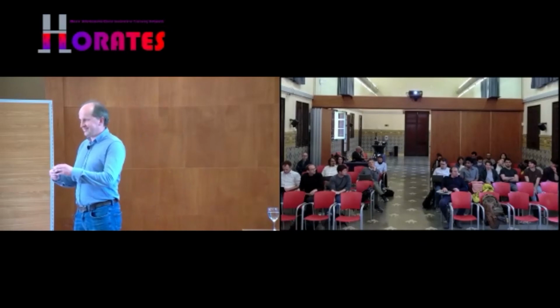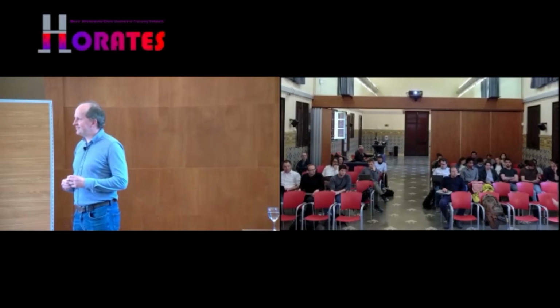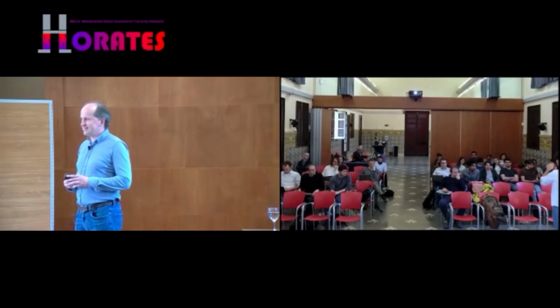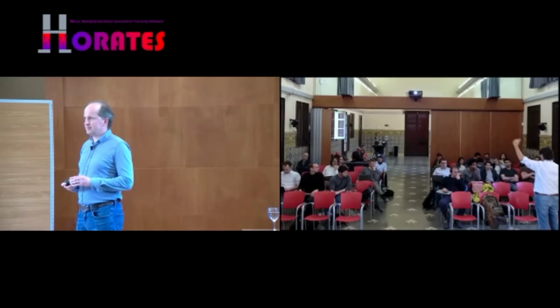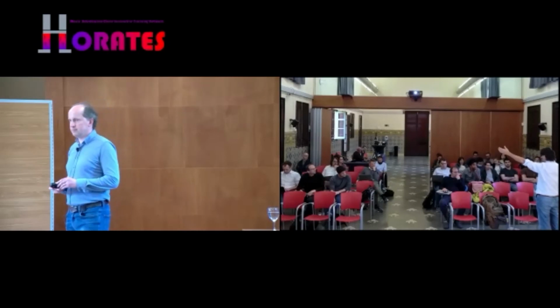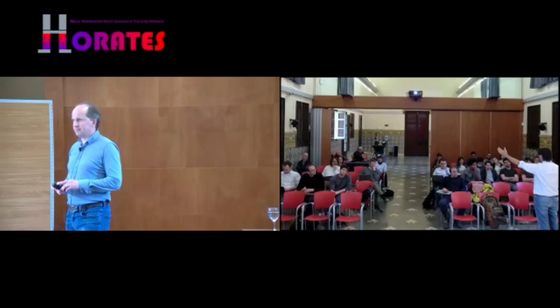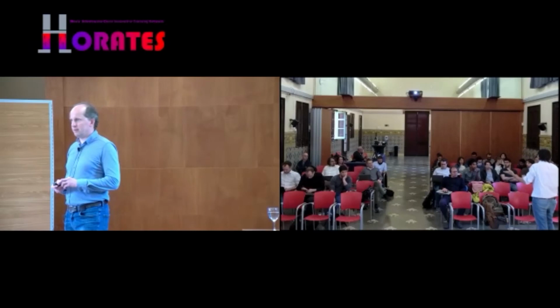Anybody else? If I may comment something, maybe I'm wrong also, but probably you focus more on the modes with the highest speed of sound, right? The modes which are flat, the dispersion is flat, the group velocity is very slow, so the contribution to the thermal conductivity is relatively low. So actually you want modes with a large slope, which are the ones that probably will carry more heat. And this is the typical comparison that you make between the longitudinal acoustic and transversal ones. The transversal ones are flat when you go to the edge, and so they do not contribute as well as the LA modes. This would be one of the ways.